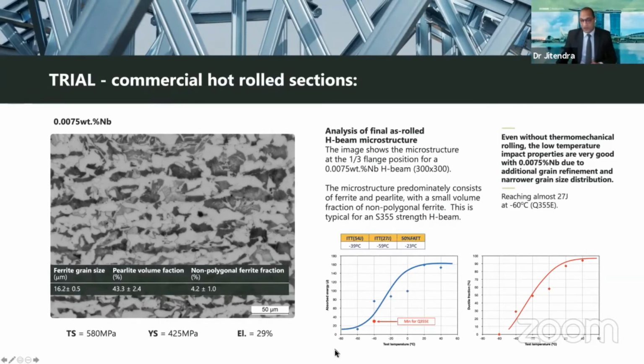And also interestingly, when we did low temperature Charpy properties, you can see in this blue line here where the red dot is, the Charpy properties actually were very good, and it almost made a very low temperature product here, which is not what was intended, but we could almost reach 27 joules at minus 60. So again, this was a very positive bonus aspect of the addition of niobium for the customer as well.